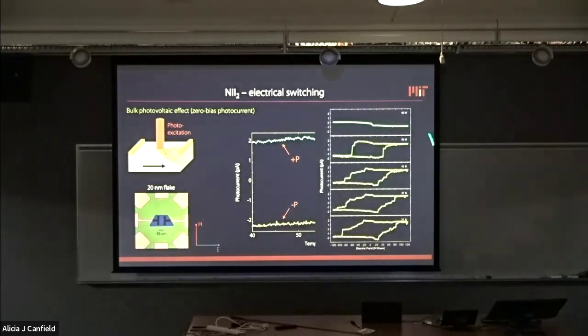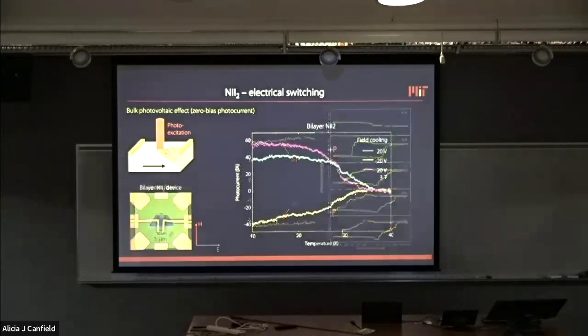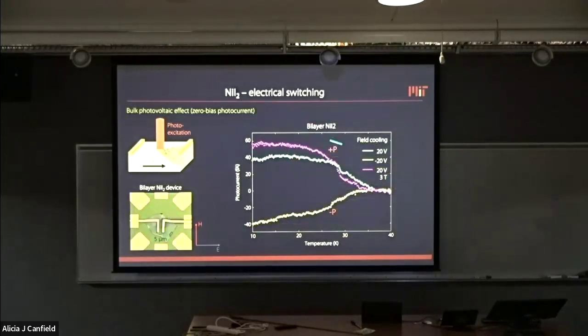And we can do switching, so we can do the whole ferroelectric hysteresis loops. And this is as a function of temperature, so everything goes away at 60 Kelvin, but then you develop these nice and square ferroelectric hysteresis loops. There is maybe a little bit of domain wall motion that causes these sudden jumps in the ferroelectric hysteresis, but otherwise it looks legit. And we can measure this all the way down to bilayer, and in fact also monolayer.